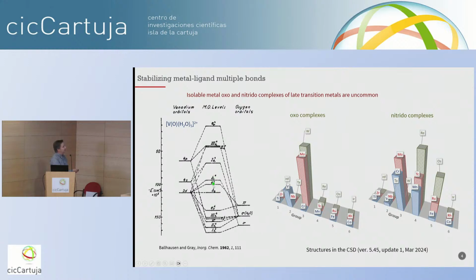What's really important here are the metal-based orbitals and the resulting molecular orbitals. We have this one set here, which, if your z-axis is along the vanadium-oxygen bond, is going to be the dxy orbital that's completely non-bonding. Every other orbital here has some anti-bonding character to the ligands. And notice that this e pi, the pi star orbitals of the vanadium-oxygen bond, are the next highest. So in this case, if you have up to 2 d electrons in here, you can accommodate that without populating anti-bonding orbitals. But the moment you have 3 electrons or more, you start to lower the bond order of that metal ligand multiple bond, and that leads to lower stability.